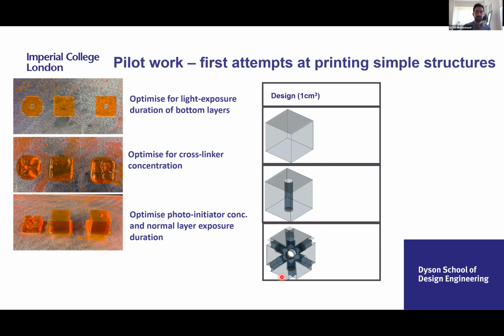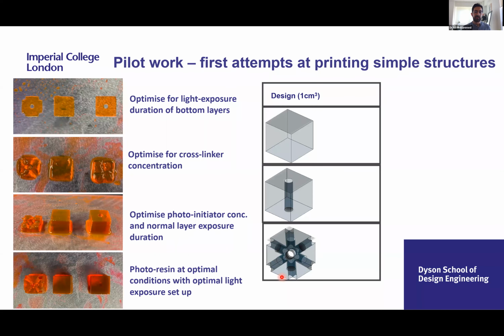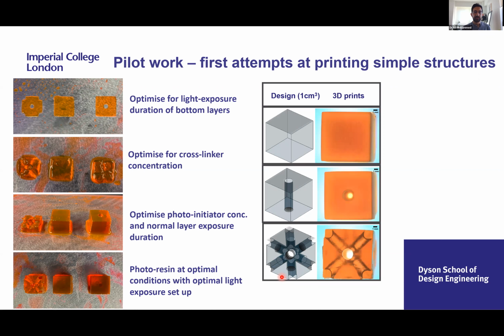So we optimized the photoinitiator concentration and the normal layer exposure durations, which finally resulted in the first successful green light printed structures. So we have a photoresin in an optimal condition, with a specific optimal light exposure setup for that resin. And as you can see here, in a comparison between the CAD designs and the 3D prints, they're very, very similar.